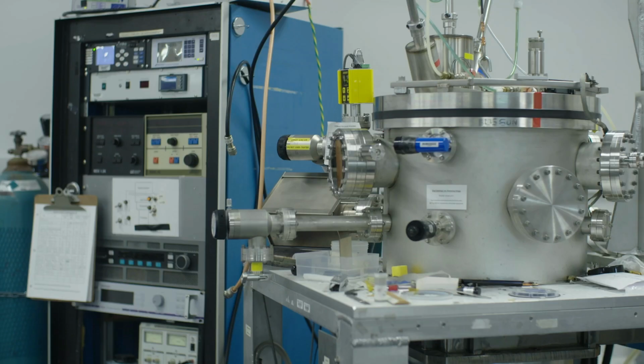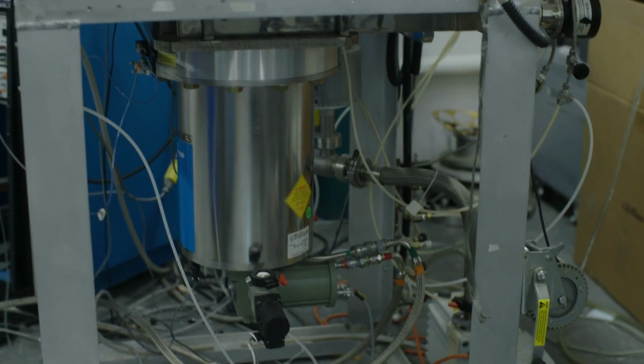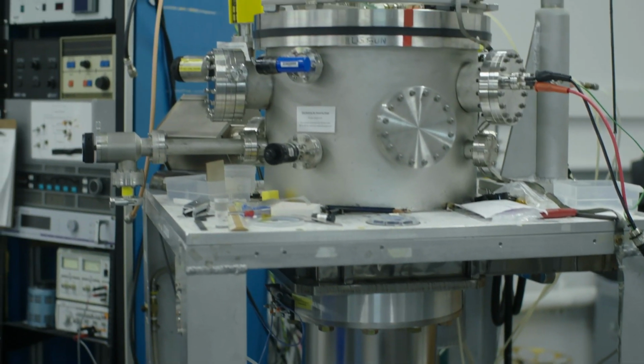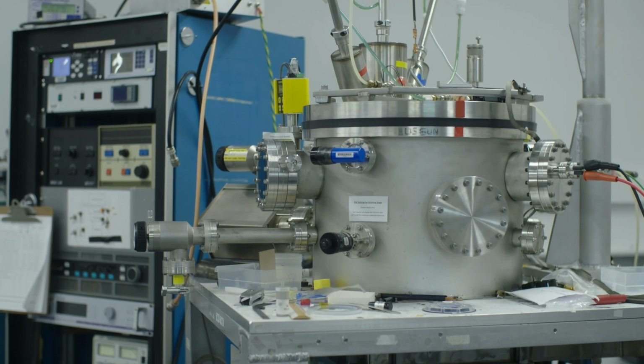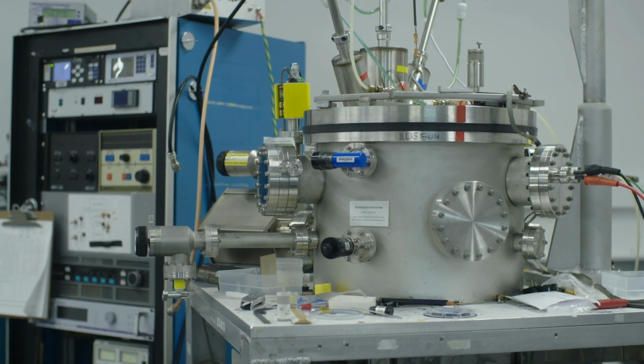And so the trick was, what Nate figured out to do was, we made a thick chrome layer that was dark and ugly, and then he used a different set of process parameters to put a thin layer on the top of that was nice and shiny. So it was still all chrome, still met their requirements. And then once we had those process parameters worked out, then we could transfer that to a different machine at CCMR where they could make many of these things at different thicknesses that could provide Calmetrics with some raw material they could use to make their calibration standards.